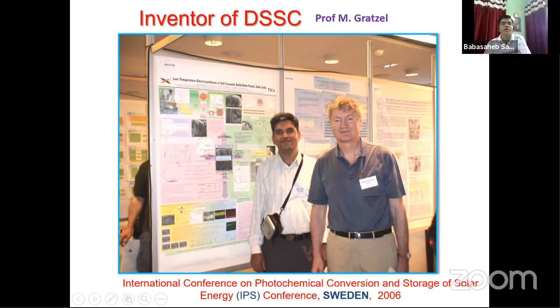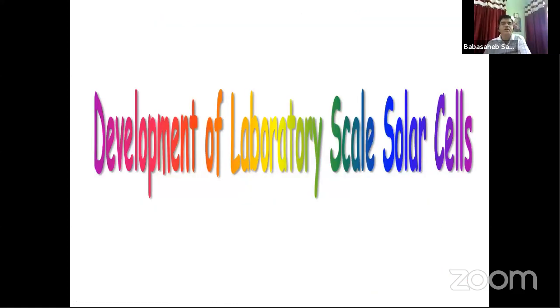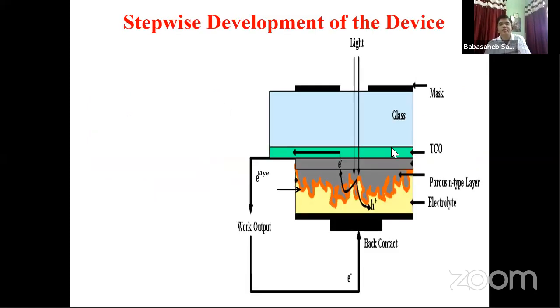Here I wish to demonstrate how we can make a laboratory scale solar cell by using simple nanomaterial. Here you can see the schematic: you can have a glass TCO, then one layer called a compact layer or seeded layer. Then you can have a very high surface area wide bandgap semiconductor. The red color is for the coating of the dye molecules on the high surface area. Then electrolyte and back contact.